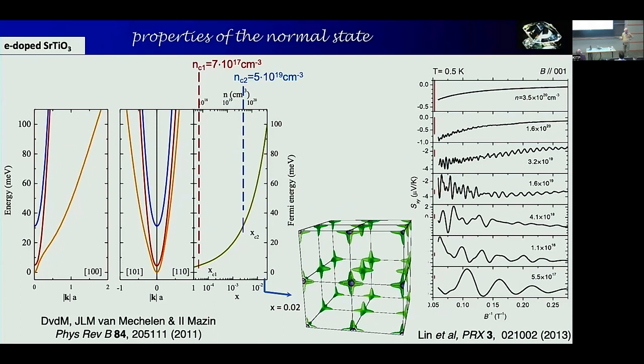No, I'm just going to ask a simple question. Just for my own information, the band splitting, is that purely from the octahedral tilting transition? This one is from the octahedral tilting, and this is spin-orbit coupling on the titanium 3D. So the spin-orbit gap is bigger than the... Yeah, it's about 30 milli eV. That's the Wien code prediction.